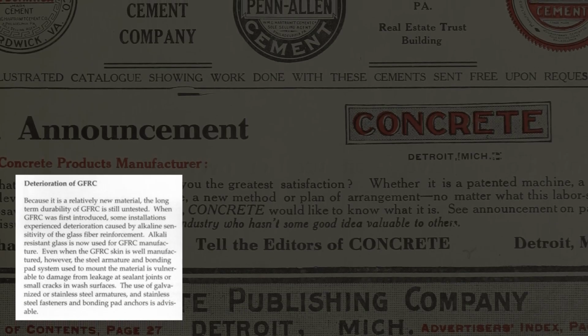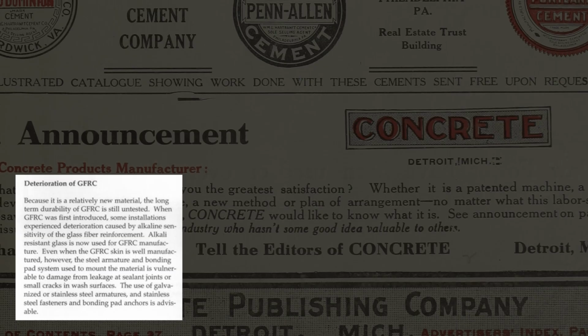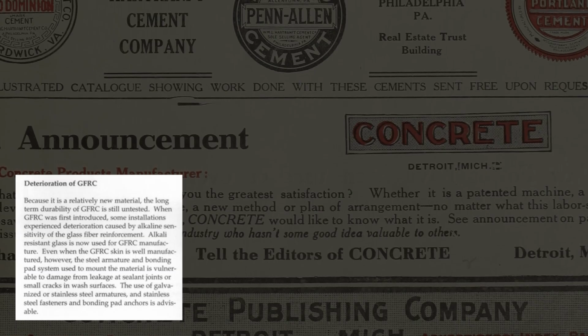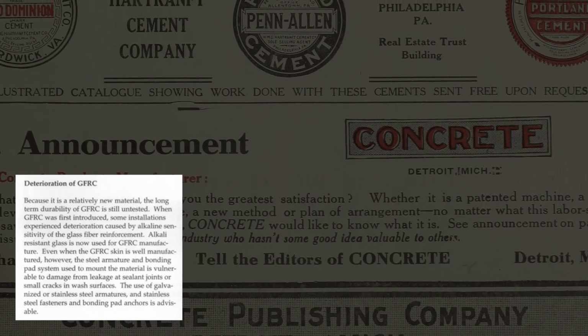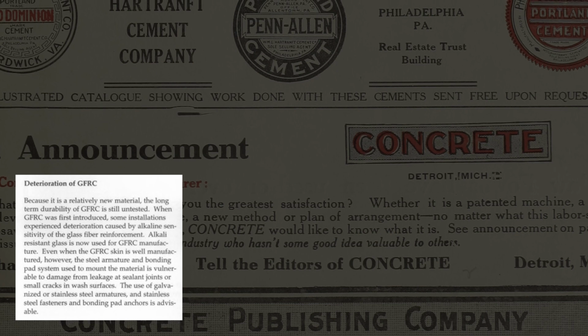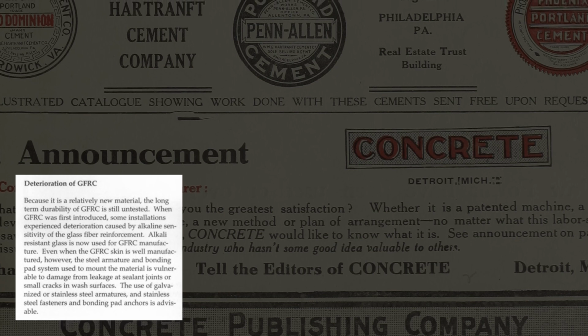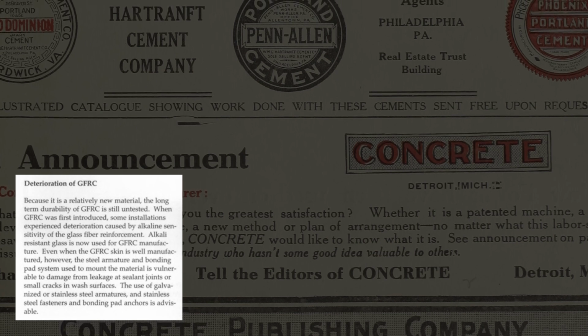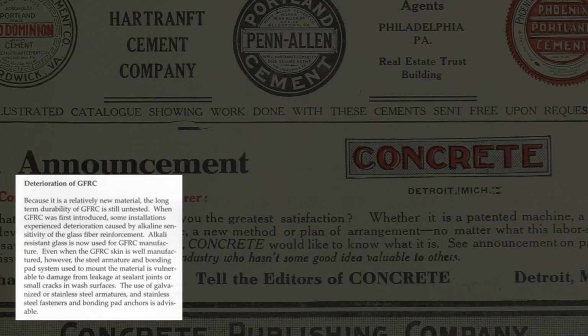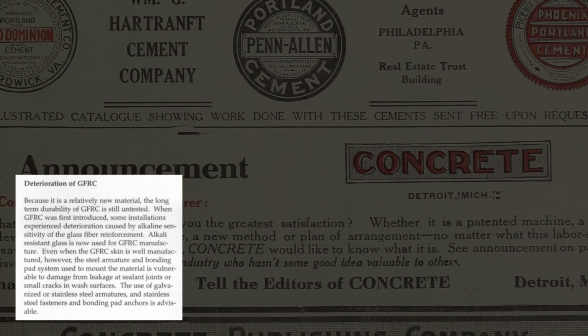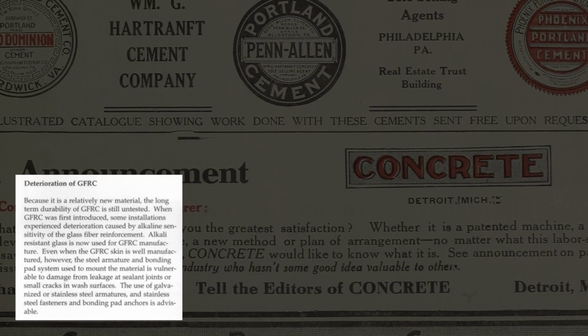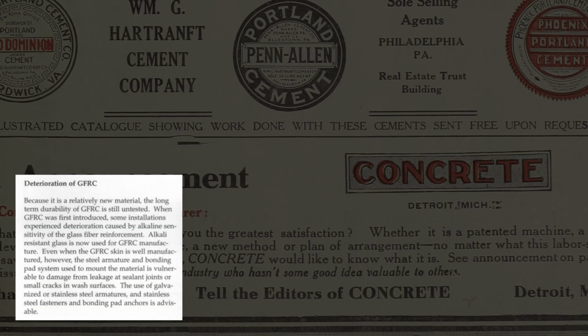Even when the GFRC skin is well manufactured, however, the steel armature and bonding pad system used to mount the material is vulnerable to damage from leakage at sealant joints or small cracks in wash surfaces. The use of galvanized or stainless steel armatures and stainless steel fasteners and bonding pad anchors is advisable.